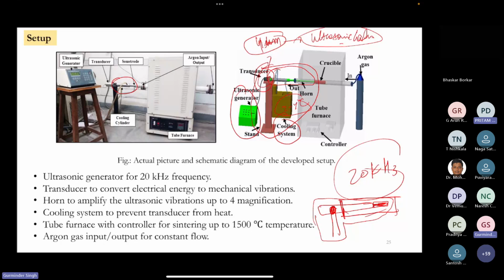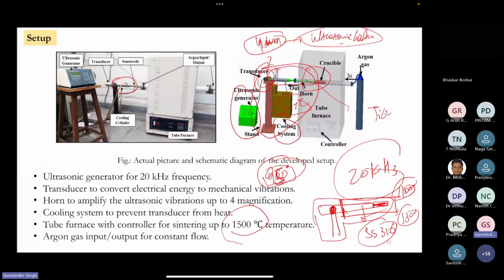There is a limitation. This horn is of stainless steel SS 316, which you can't use above 1300 degrees Celsius because it has vibration lag starting from 1100 degrees Celsius. We have done it at only 900 degrees Celsius. The furnace can work up to 1500 degrees Celsius, but we have only done work at 950 degrees Celsius maximum, because otherwise you need a titanium Ti64 horn which can go to higher temperatures.